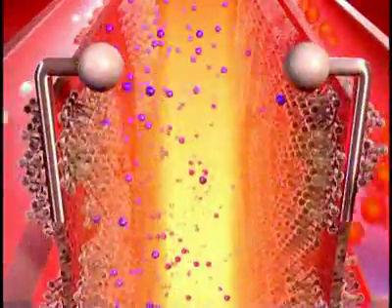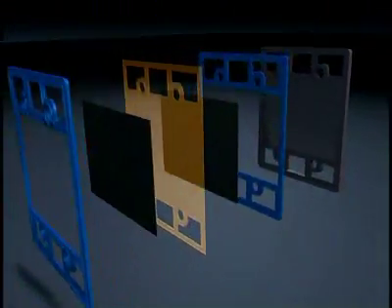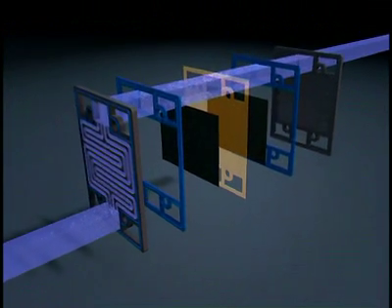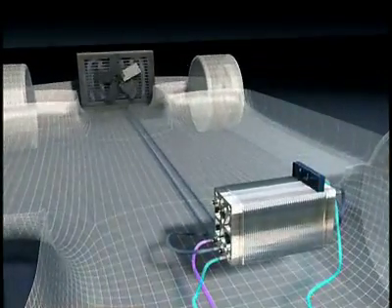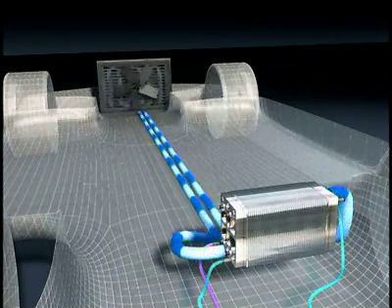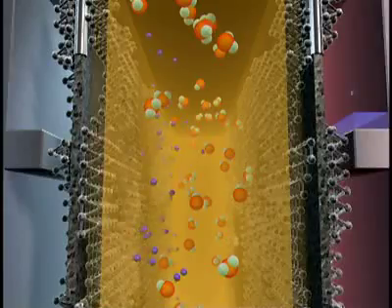When temperatures inside the fuel cell reach just over 100 degrees Celsius, the water stored in the membrane turns to vapor. That interrupts the charge exchange, and electricity stops flowing. To keep electrical flow constant, each individual cell has to be painstakingly cooled. The cooling system ensures that the collection of fuel cells as a whole doesn't exceed temperatures of 80 degrees.